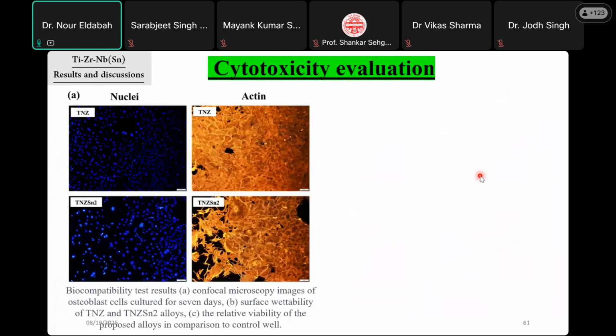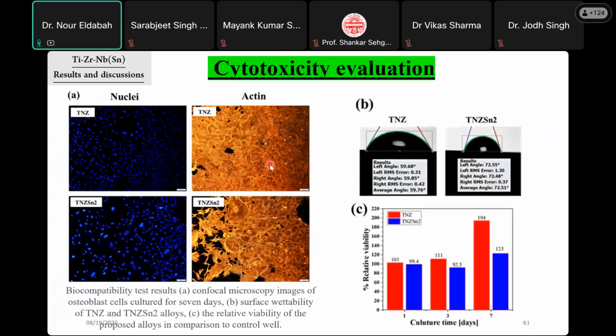For the cytotoxicity, because we selected biocompatible elements, we can find healthy cells. This is the nucleus of the cell, and this is the full cell. And we have a hydrophilic effect of the surface, so we have obtained a very high cell viability for both alloys.